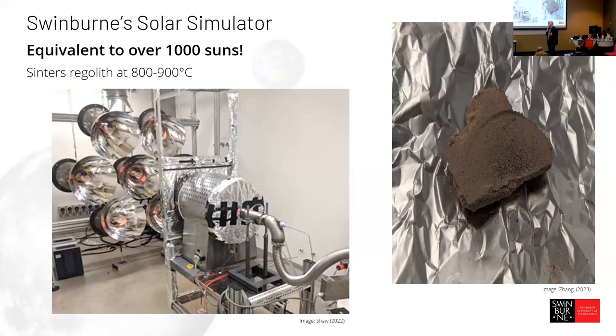There's a number of things that can improve a ceramic. One thing is the way that the particles are combined. If you can get the particles interlocking with each other, the different sizes, then you've got a better chance of getting a final better product. If you can take out some of the very large particles that break up the network, you can also get a nice sintered sample. So we started looking at things like that.